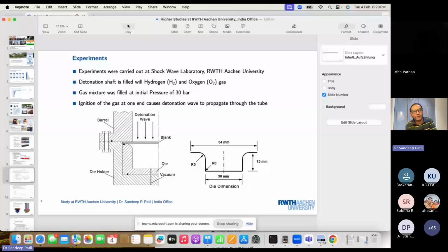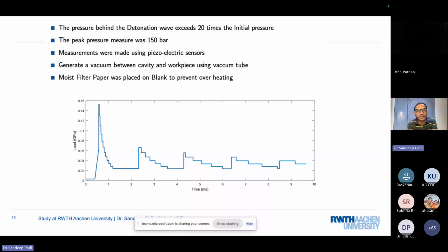Here, the pressure behind the detonation waves exceeds 20 times the initial pressure. The initial pressure is 30 bar, but the peak pressure of this experiment goes up to 150 bar. The measurements in this experiment were made with a piezoelectric sensor. And as I said, we avoid the negative pressure by using the vacuum tube, and sometimes we put a moisture filter paper on the blank on the gas heating side, so that there is no overheating of the blank at the surface.